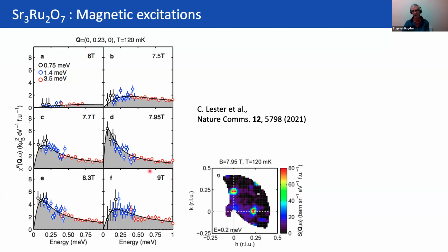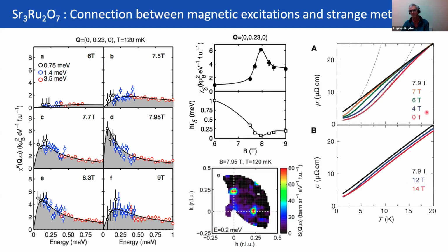So this is the spectra measured at the incommensurate position here. When these low energy spin fluctuations are there, we find that the low temperature resistivity becomes linear quite dramatically. So you can compare the susceptibility that comes out while fitting this low energy contribution to the spin fluctuations. This is the susceptibility, chi, the real part of susceptibility, and you can see that it gets larger as we go across, as you might expect. Okay, so that's just to show you that there are systems, also heavy fermion systems, where the presence of low energy spin fluctuations goes hand in hand with linear resistivities, particularly at the lowest temperatures. So the question is, is there something similar happening in the cuprates?